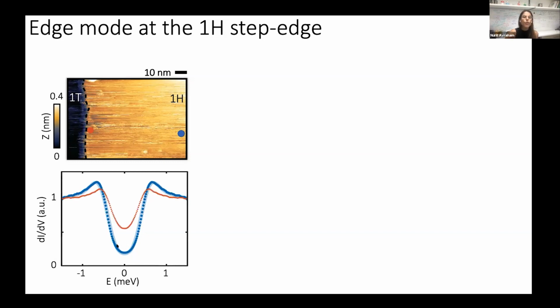So we see a huge increase in the density of state at the zero energy, and we see a very slight reduction in the gap that is shown around here. And when we try to fit it again by a BCS plus an offset and account for this small reduction, it doesn't account for the huge increase that we see in the zero bias.